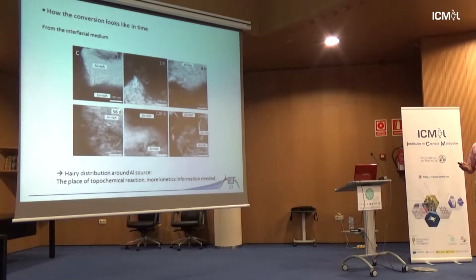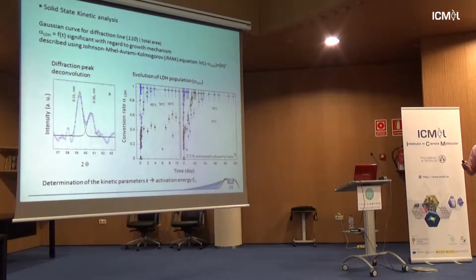That's the observation, and we were quite keen to know, for this topochemical reaction, quite unusual to unravel, what the kinetics information was, because we wanted to know what kind of mechanism is behind that. So to do that, and that's the reason the value is quite small but still we can refine, we refine the position of the LSH and the position of the LDH all together at the intermediate time at which you have both together, LSH and LDH.